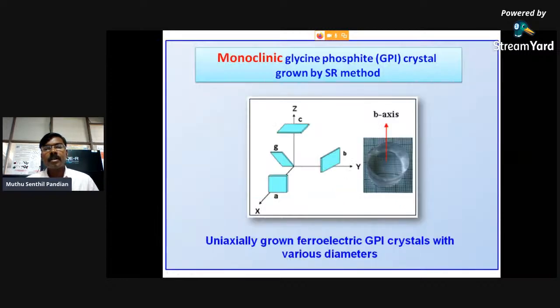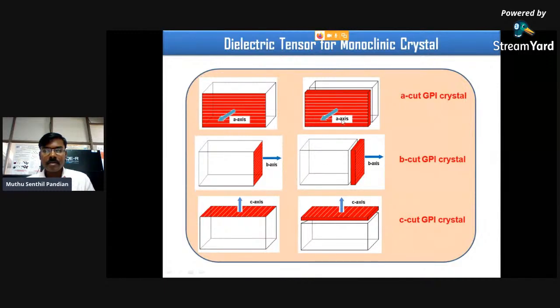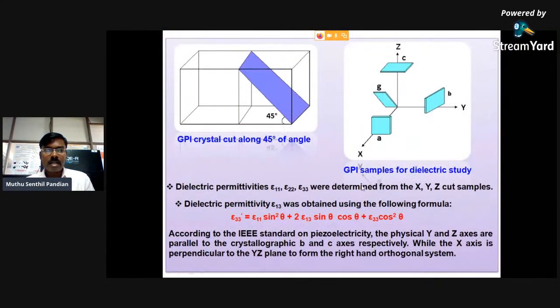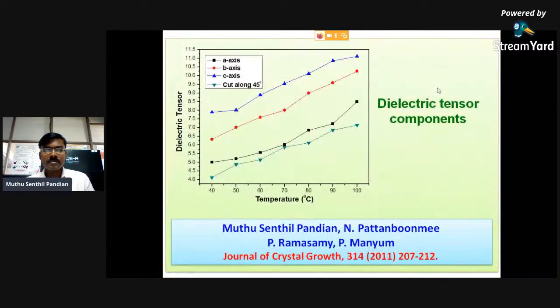So this is the monoclinic glycine phosphite single crystal. Here we have grown the crystal along its polar B direction, and we have cut the crystal along its A, B, C directions, and 45 degrees perpendicular to the B direction. So this is the fourth tensor value. We carried out the dielectric permittivity measurement along four different directions. And here also we can see the dielectric tensor values for the glycine phosphite single crystals grown by the SR method.